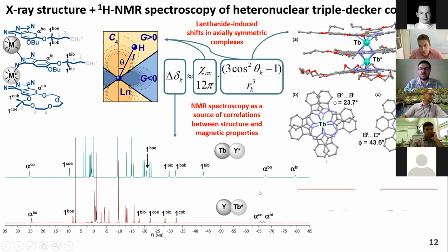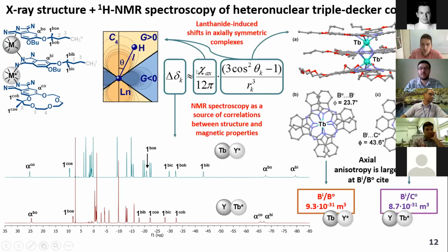We used this NMR spectrum to extract axial anisotropy parameters, and we see that actually the axial anisotropy in the distorted state, here for terbium between butoxy groups, is approximately 10% larger than in the case of the metal ion located in the square antiprismatic arrangement. As far as we know, such an increase of axial anisotropy can gain us several hundreds of K in terms of the relaxation barrier.